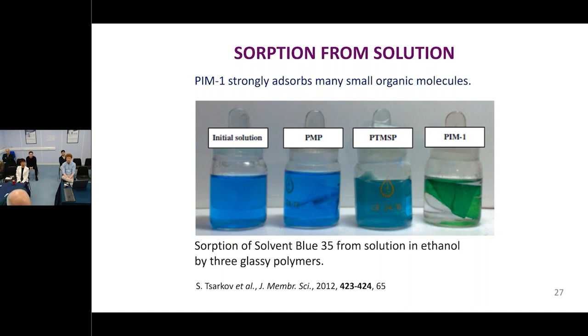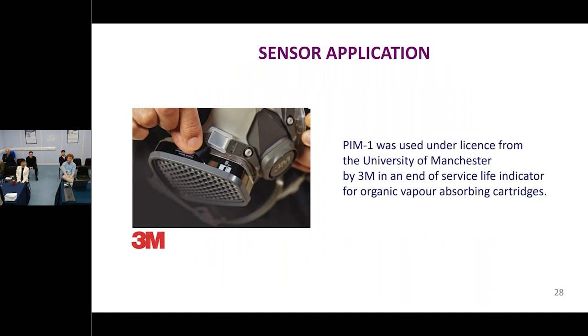And that actually is the reason for its first commercial application. Unfortunately, this is no longer available for reasons which have nothing to do with the polymer. But 3M created a little sensor which used PIM1, thin film of PIM1 at its heart. And this was used as an end of service life indicator for the cartridges they use for absorbing organic vapors that are used by people who work in environments with lots of organic vapors. And the idea is that this little sensor tells you how much of the carbon is used up and when it's time to change the cartridge.